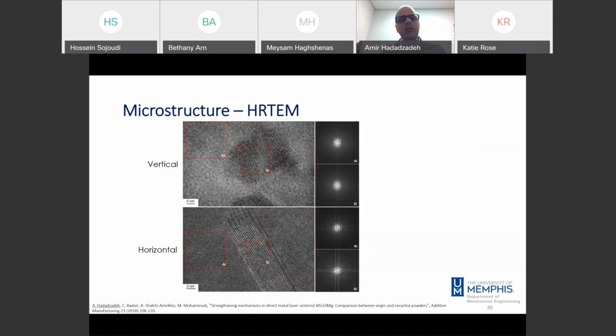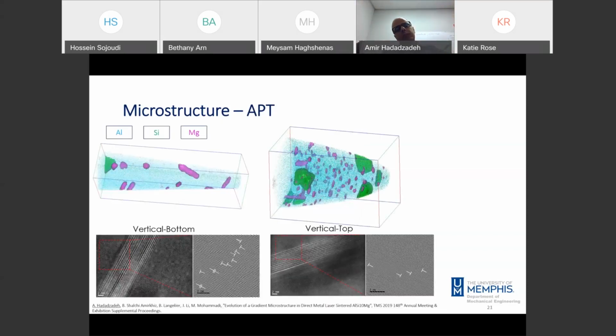I studied the silicon precipitates using high-resolution TEM, and we can see the atomic structure, and there is a crystallographic relationship between the aluminum matrix and the silicon, as you see in this picture here. Another way to study the precipitates is using atom probe tomography. In the APT technique, we can study the chemistry of a material atom by atom. And here, in the case of the vertical sample, this is a separate study, but it's quite interesting in terms of analyzing the microstructure consistency in AM material.